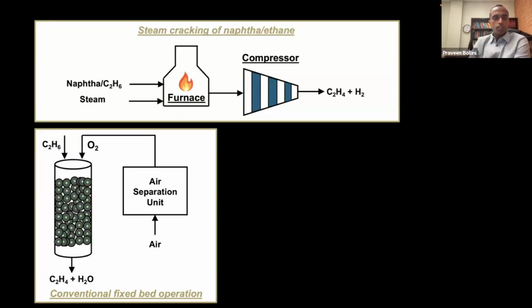One alternative that's been proposed in order to get around this pressure requirement is to co-feed oxygen and create an exothermic process that is not thermodynamically limited and produces, let's say, ethylene and water at low temperatures, hundreds of degrees Celsius lower than the steam cracking process. The disadvantage, however, of doing this in a conventional fixed bed, as is typically evaluated, is that you need a large capital intensive air separation unit to generate pure O2 that is then fed to the oxidative dehydrogenation reactor.